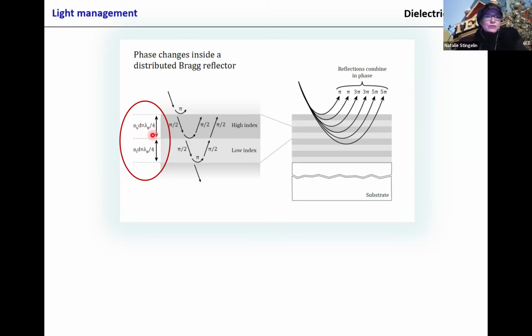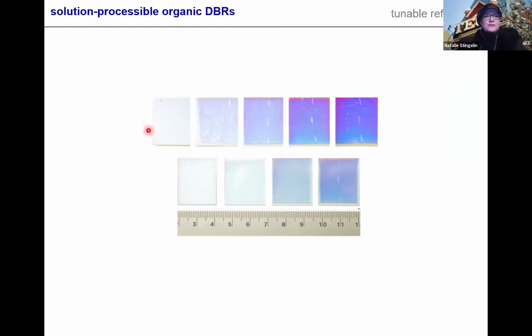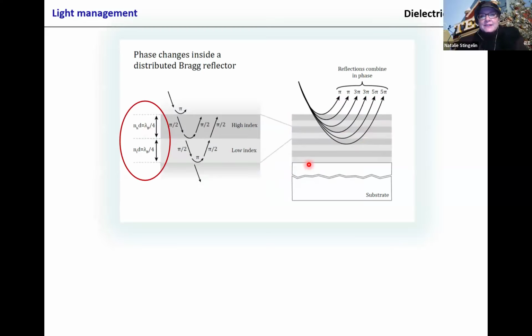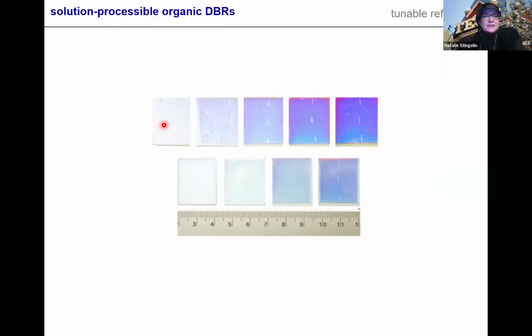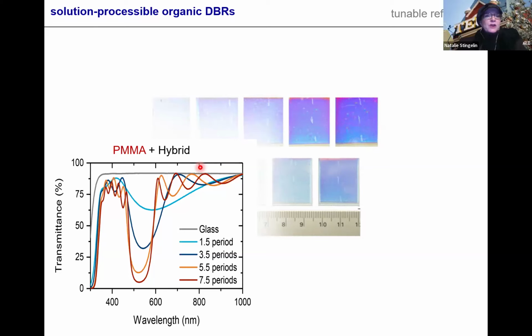And if you want to reflect or use this structure to do something on light of the wavelength lambda naught, you have to have this thickness be 1/4 of the wavelength. And if you now stack them up, as shown before, 1 layer, 2 layers, 3 layers, 4 layers, you see how light starts to be reflected in a specific area, in this case, blue. And you can follow that.